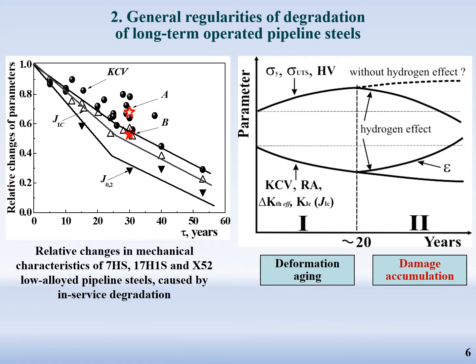Embrittlement. Deterioration of mechanical and corrosion properties is often the result of in-service degradation. Based on our previous results, we can distinguish two stages of in-service degradation of low carbon and low alloy structural steels. Stage 1, deformation aging, and stage 2, in-bulk material damage accumulation, or so-called dissipated damaging.